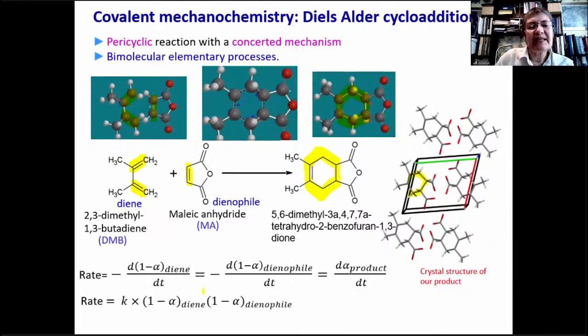So these are the rates that we expect. This is the conversion fraction of the product obtained versus the time. And we expect that the rate of product formation is equal, but with the sign change, to the rate of decrease in the amount of the diene, the 2,3-dimethyl 1,3-butadiene, and the same for the maleic anhydride. So then we expect this rate to be measured, and we are working on that.